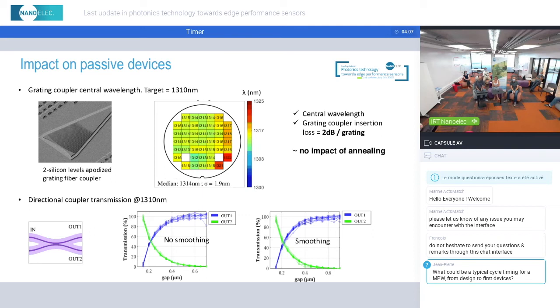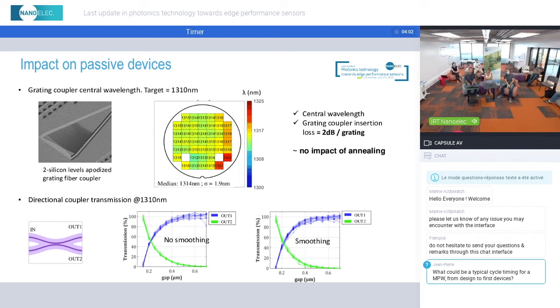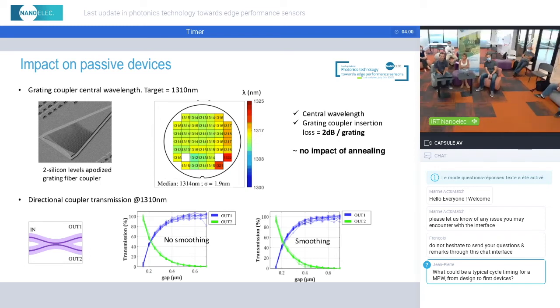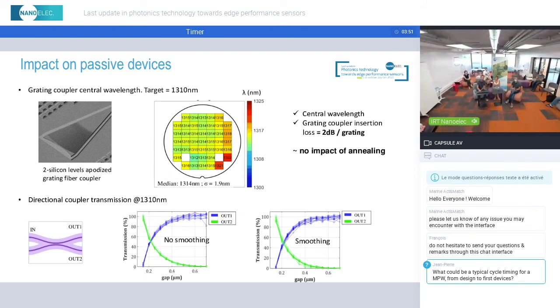So for us, it's very good. That means that we don't change much the central wavelengths, and we can still work with the wafer after this annealing. In terms of insertion loss, it's very good too. We have 2 dB loss per grating. The second device is a directional coupler. Again, you can see by comparing without smoothing and with smoothing annealing that the transmission as a function of the gap between the two waveguides is steady.